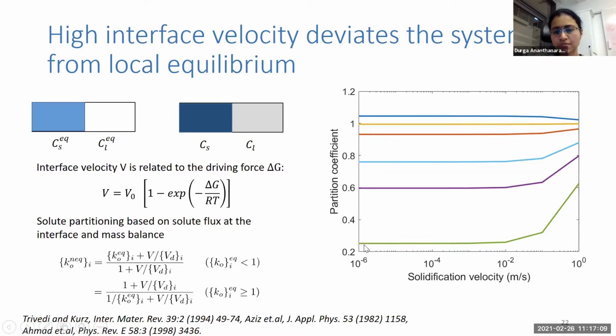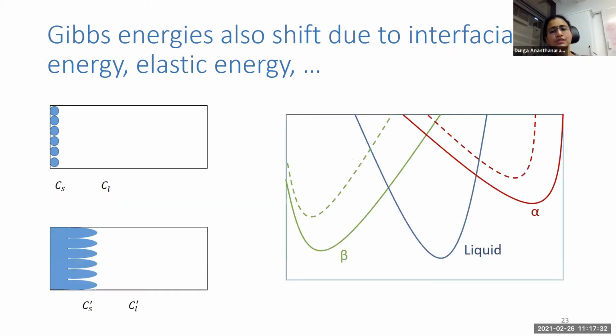But just to show what happens, if we have different partition coefficients, ranging from 0 to 1 or above, then at higher and higher velocities, all of them go towards 1. So at very, very high velocities, like we have in glass forming conditions, we'll have a partition coefficient of 1. So that was about partitioning and non-equilibrium effects.